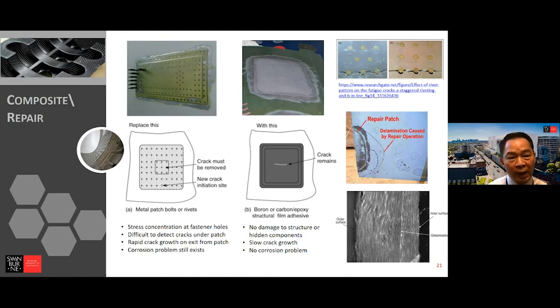And that introduces something like a crack along all the rivet holes. It's like a stamp, you can tear off easily with so many holes. But for the composite patch, it's much easier. And then they put adhesive in between the layers. This kind of adhesive also tries to close the cracks as well.